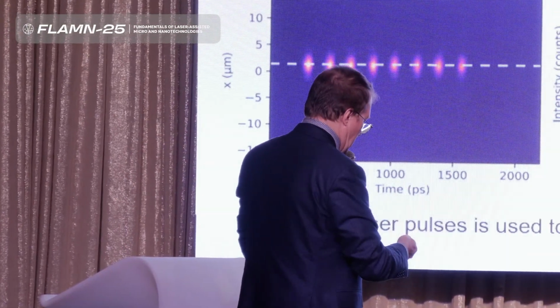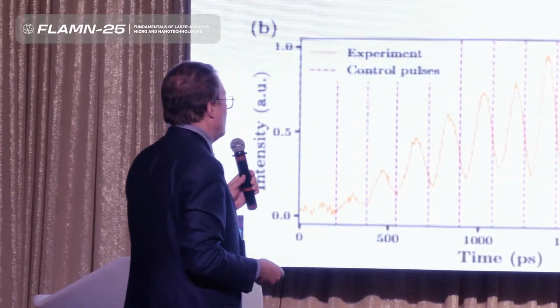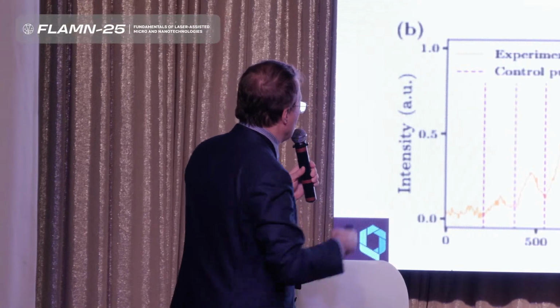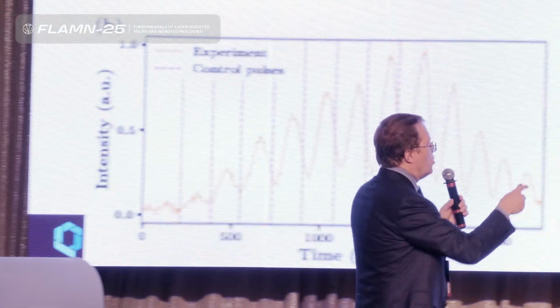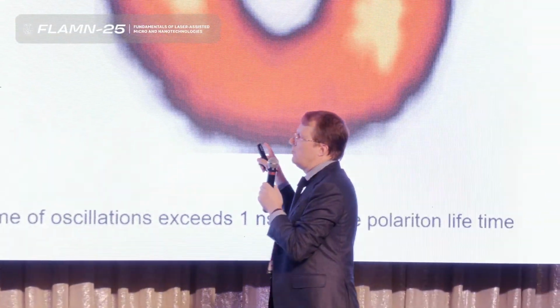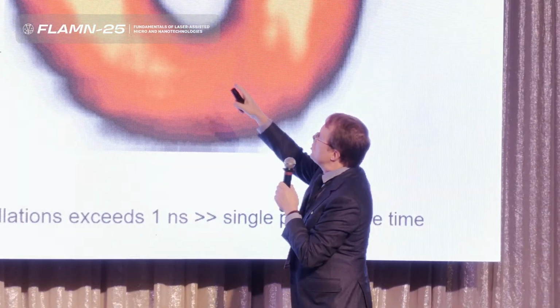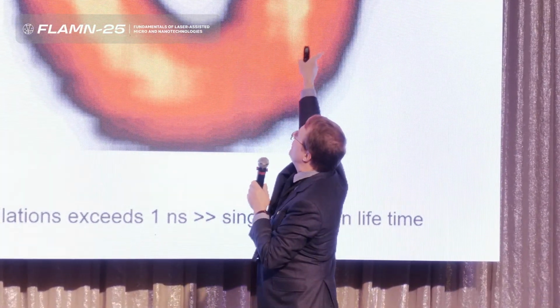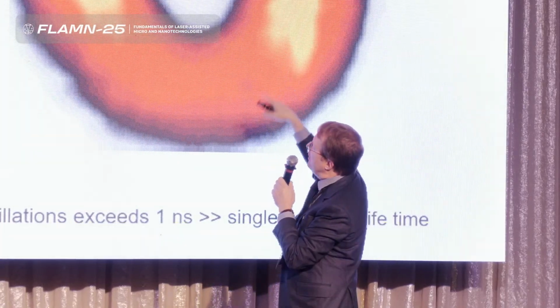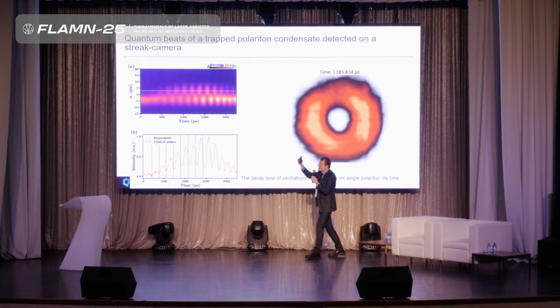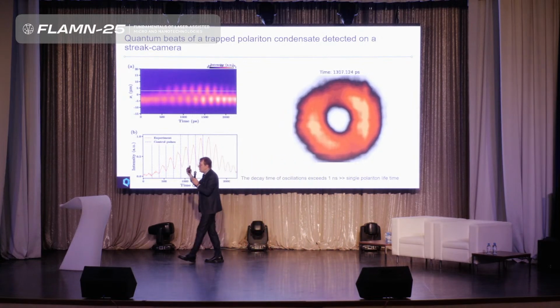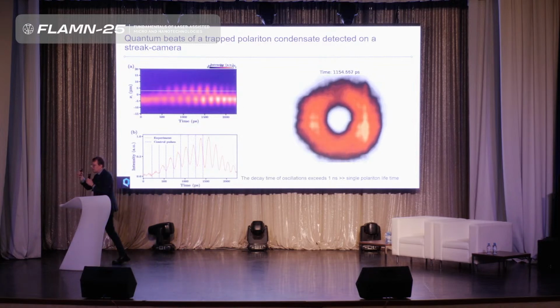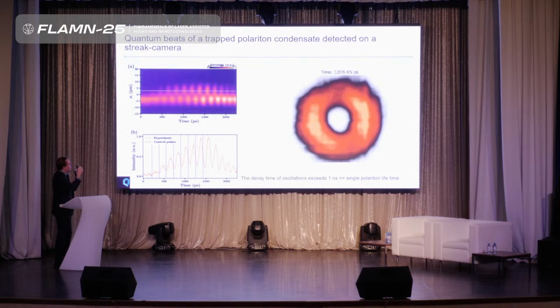And with this, really, you move your state from one of the eigenstates of the trap to the superposition state of the trap. And when you have a superposition, you can observe, first of all, Rabi oscillations, of which I have already shown you some images. You see how in real space your condensate oscillates. So this donut is an experimental image obtained with a streak camera. And it is a superposition of this p-shaped wave function, p x, which is horizontal, and p y, which is vertical. When you put them together, it gives a donut, but still you see oscillations because your trap is elliptical. There is some splitting between them, and you see oscillations at the frequency given by this splitting. You can see it in real time.